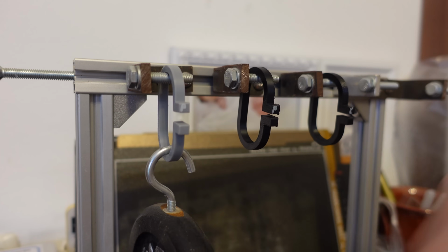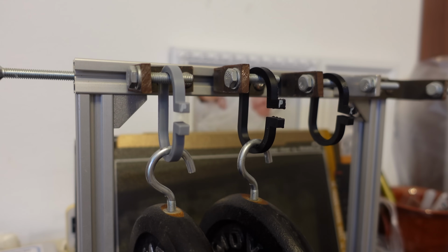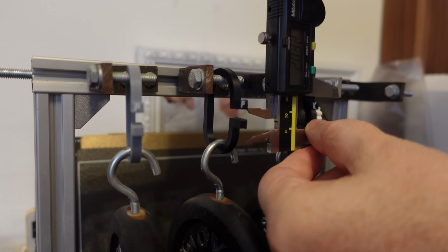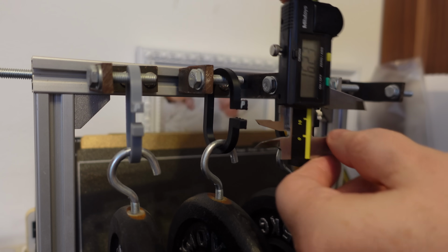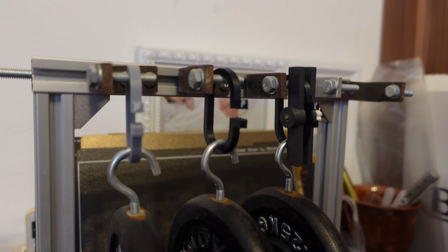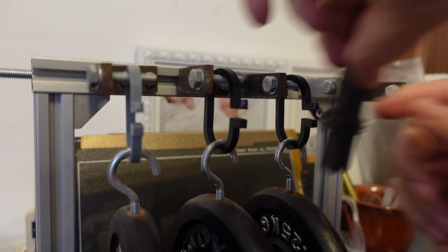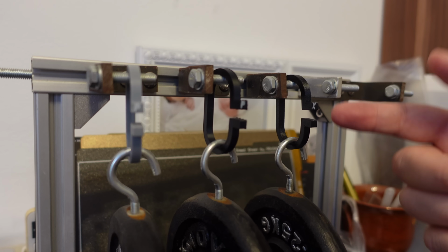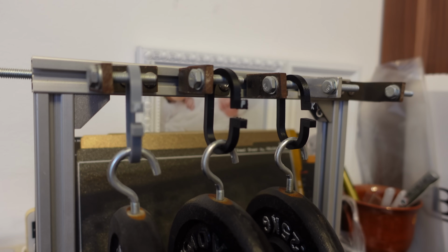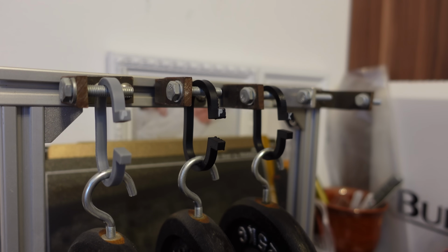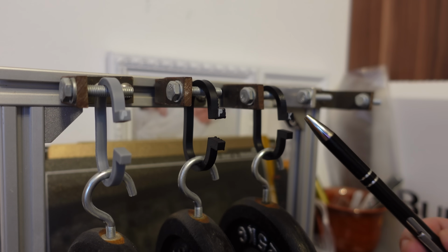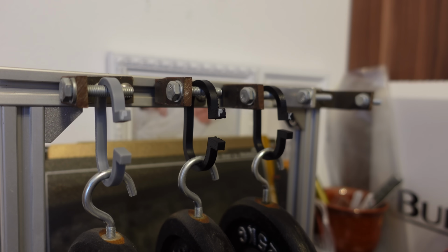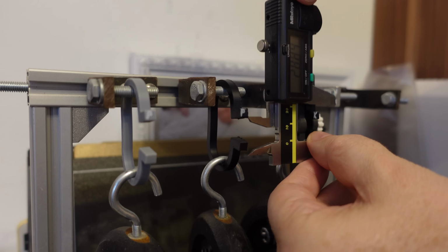2 on the left are PLA filaments, and the last one on the right side is this ABS. 16:23. Quite big deformation for the fiber reinforced material. Day 5 and typical behavior. Initial deformation was bigger on this ABS, but now after 5 days, even with the bare eyes, we can see more deformation on PLA materials. And this is typical for these filament types.